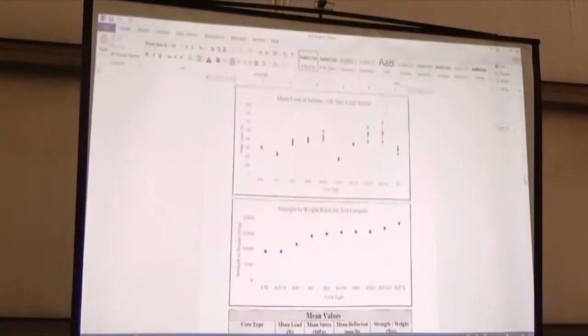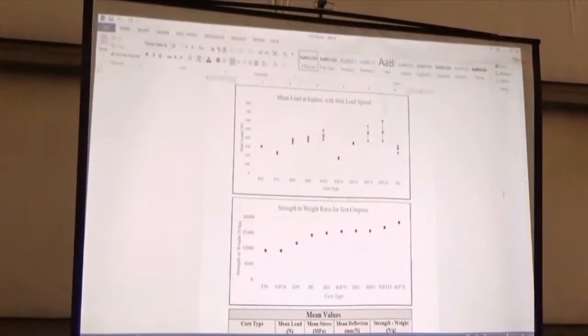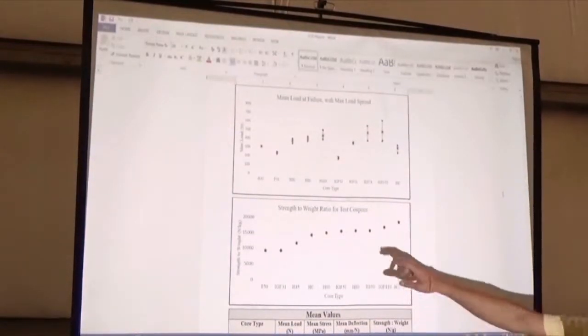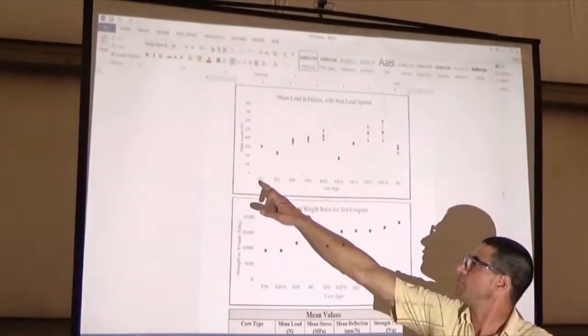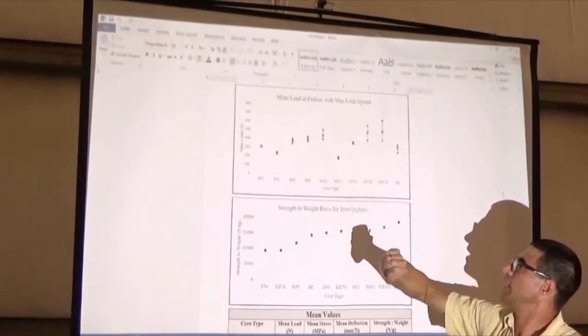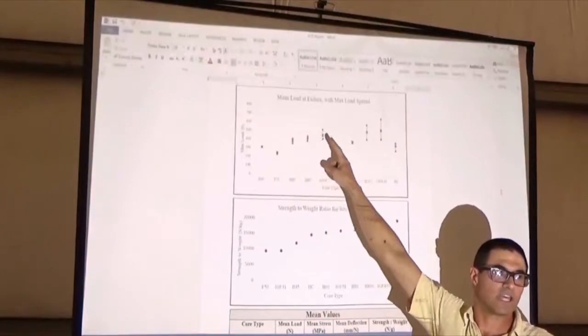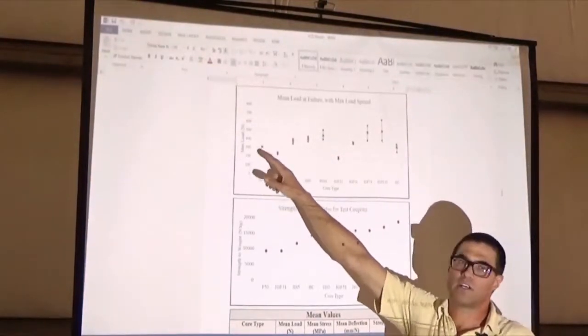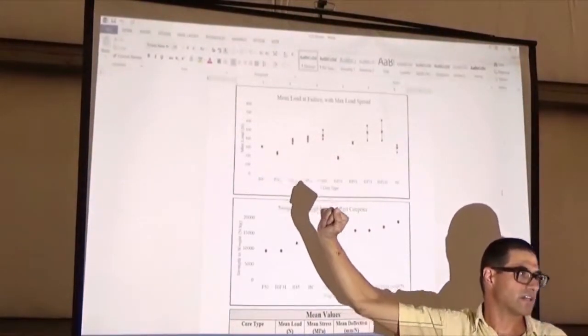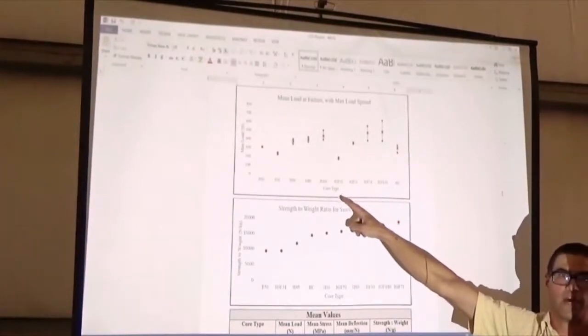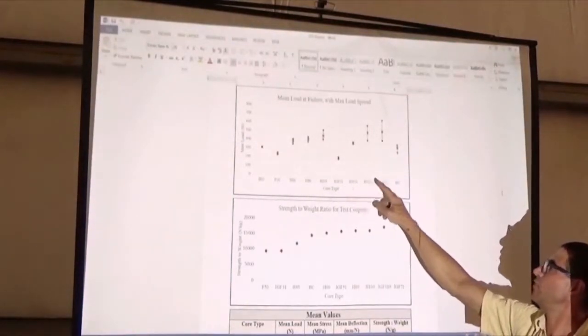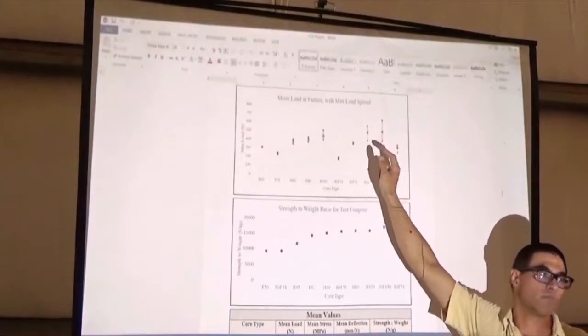So we tested all of those foam cores, and this is a summary of all of the different cores. This is Divinycell 45, 50, 60, 80, and 100, and you can see as the density goes up, we get stronger, they achieve a higher and higher load. Same with the IGF, 51, 71, 110, that's also going up.